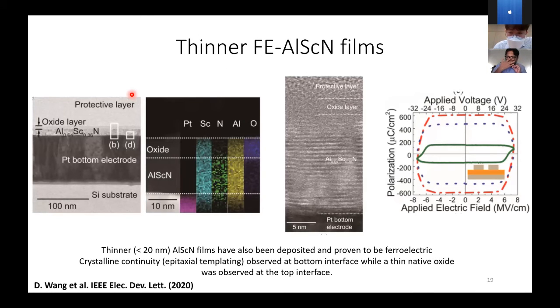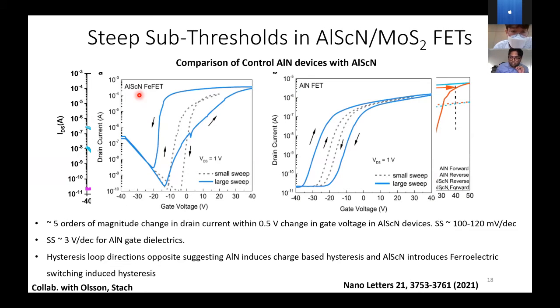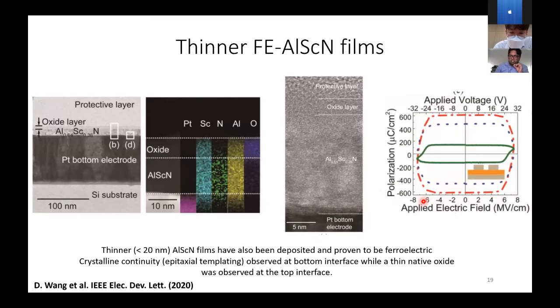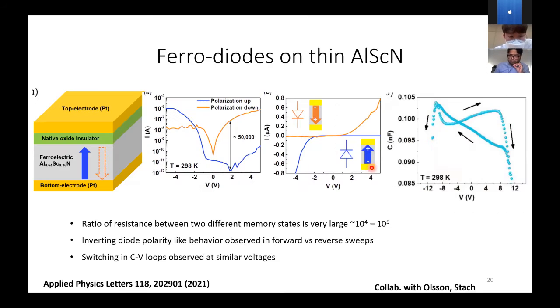So the other big question we want to ask and answer is, can you make these ferroelectric films thinner, right? Because if you look at the operating voltages over here, they're still not good. They are a few tens of volts. So we have succeeded in making thinner ferroelectric films. These are about 20 nanometer thick films of aluminum scandium nitride. And in these films, there are no more 2D materials here. This is just a simple MIM device.